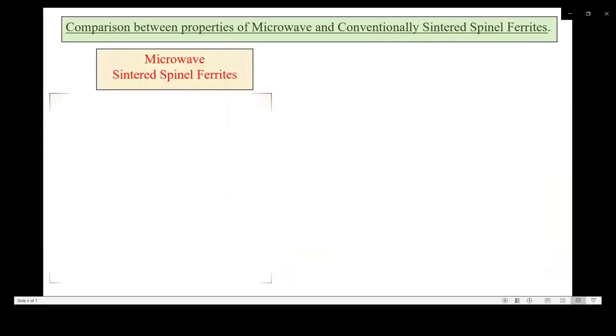Here I have compared the properties of microwave sintered spinel ferrites and conventional sintered spinel ferrites. The process of densification is accelerated in microwave sintered spinel ferrites, whereas in conventionally sintered spinel ferrites, the process of densification is slower. The dielectric constant of the material processed by microwave sintering is lower as compared to the dielectric constant of the material processed by conventional sintering. Also, it has been observed that the coercivity of the spinel ferrite is decreased as compared to the coercivity of the conventionally sintered sample.